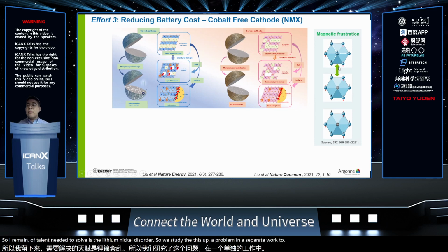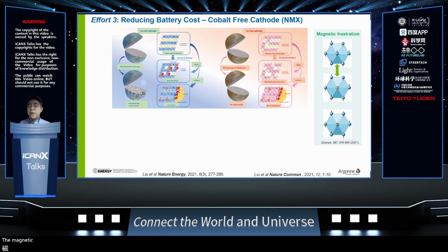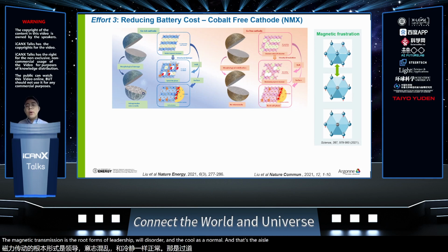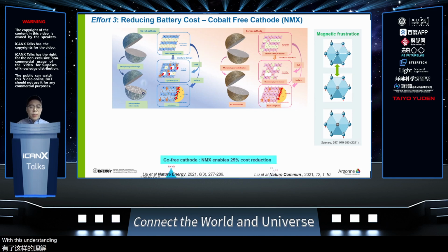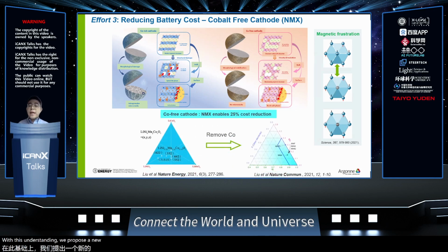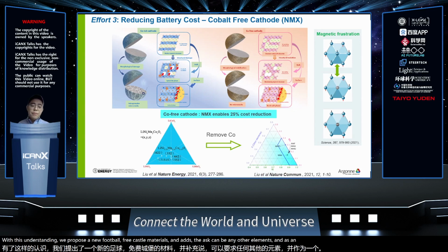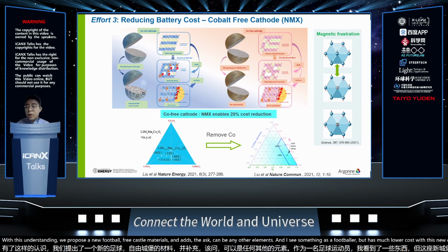We found out magnetic frustration is the root cause of lithium-nickel disorder, and cobalt, as a non-magnetic ion, can well suppress the lithium-nickel disorder. With this understanding, we propose a new cobalt-free cathode material, NMX. X can be any other element that has a function like cobalt but has much lower cost. With this new cathode material, we are able to achieve a 25% cost reduction.